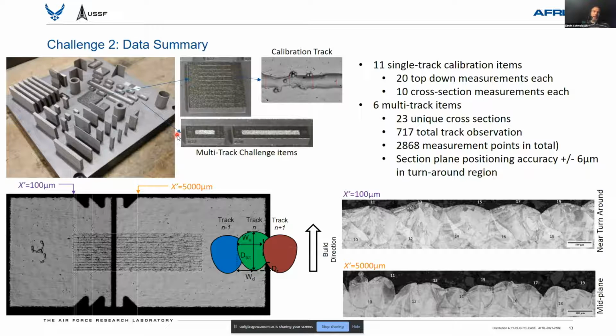So we begin to now explore some of the transient behaviors. Again, we're still looking at a very simple scan strategy, but depending on where we section and look at this object, whether we look in the very center of this multi-track or whether we come in and look near the corners where the beam is turning around and the thermal situation is a bit more transient, we can explore a range of different responses in terms of the material. So again, even sticking with simple geometries, you can really begin to push the system into very dynamic situations.